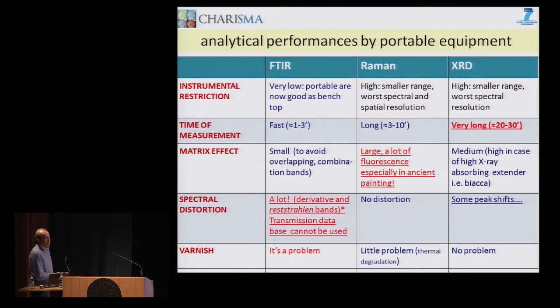And matrix effects are present. For FTIR you have matrix effects, but if you want to skip some interferences, you can use combination bands, and so in the end you can solve the problem. Raman gives a lot of fluorescence from the medium. X-ray diffraction does not show large inconveniences, but if you have extenders like biacca, for example, distributed all over the surface, the signal could be definitely decreased by the presence of lead distributed over the surface that you are observing.